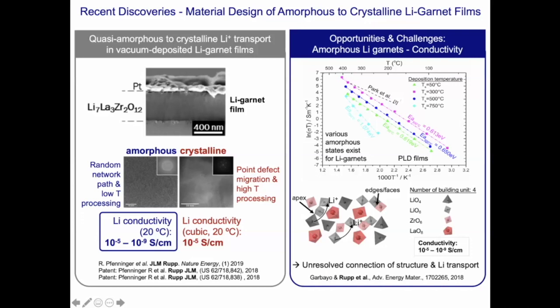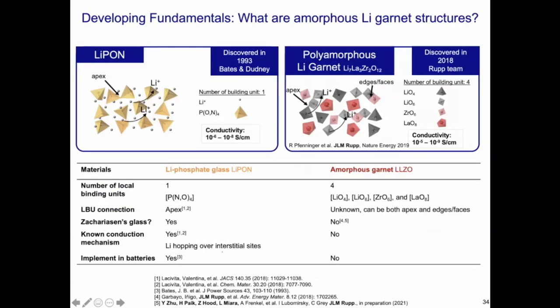And we were among the first to publish the existence of these amorphous phases for this lithium garnet material that you can find when you do classic thin film processing. We also found that the conductivity is very variable depending on what type of amorphous phase you have and is so far undescribed in literature. Now, why is this so interesting? And I want to do here a quick analogy to LiPON. So LiPON is one of the materials which has been known for 20, 30 years, which was very well developed in Oak Ridge National Labs, and which shows about 10,000 cycles of a solid state battery life. And it's in part because it's a thin film structure, it's amorphous and has no grain boundary. So it's a very interesting material to work with.